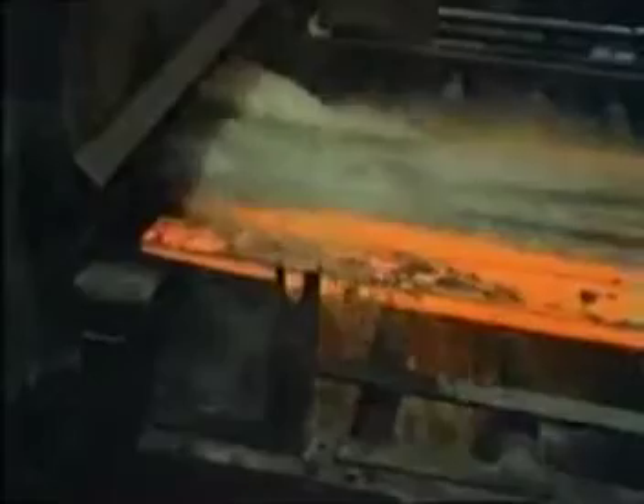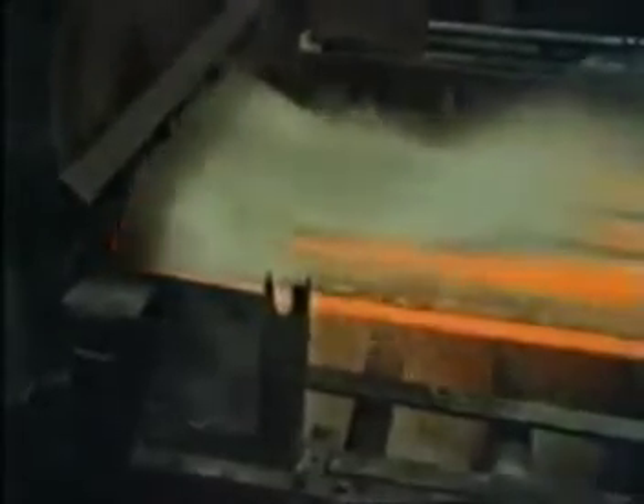The lower the alloy content of steel, the faster it must be quenched in order to obtain maximum hardness. For instance, low-carbon steels like these have to be cooled rapidly in the proper quenching solution, while highly alloyed materials should be cooled at a much slower rate in oil or some other less drastic quench solution. Most heat treaters agree that the slowest possible quenching rate that will develop full hardness is the best one to use.